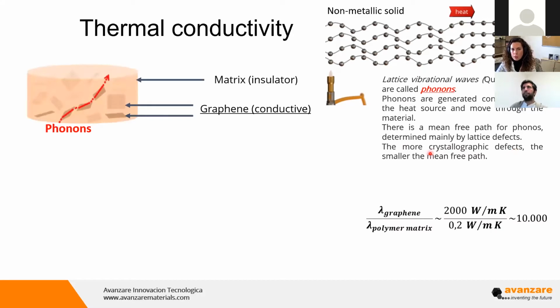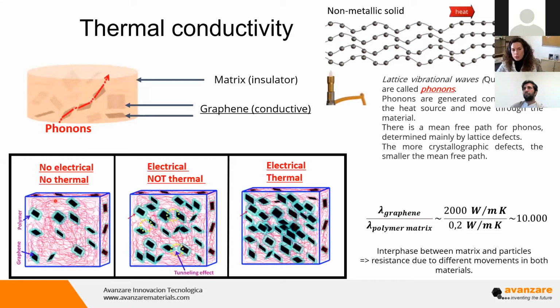When we put graphene in a material, we assume that graphene is conductive. Indeed, the intrinsic thermal conductivity of graphene is about 2000 watts per meter Kelvin, while the polymer matrix usually is about 0.2 watts per meter Kelvin, so the difference is about 10,000 times. So when we put the graphene layers in a matrix, we need to ensure contact between these layers to ensure that phonons move. When we put these layers in the matrix, we can be in these three situations. In this first situation, there are not enough graphene layers to have contact between them and let the electrons or the phonons move.